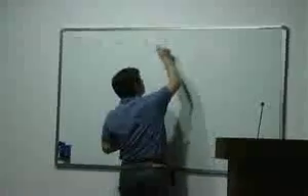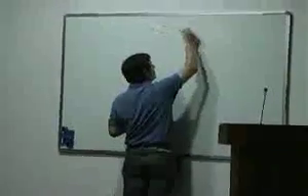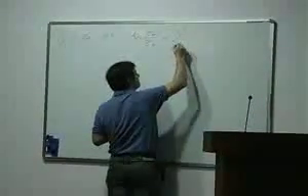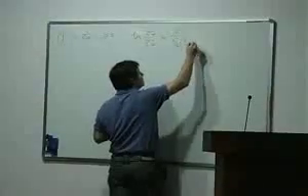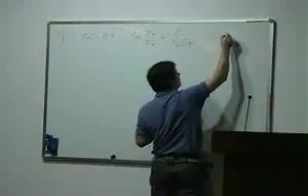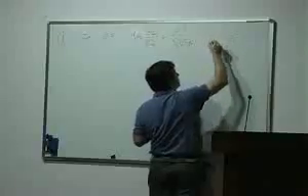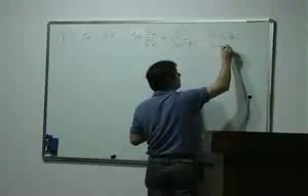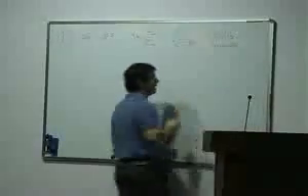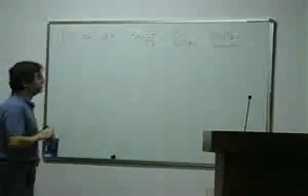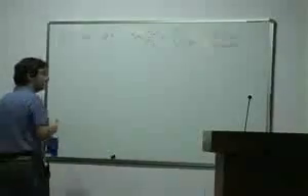And so this means that if this is equal to k squared divided by S configuration at Tg, what you get is that Sc at Tg is a universal quantity. It's the same for all supercooled liquids. Okay, so that's the first. Did I get it right? Yes. That's the first thing.